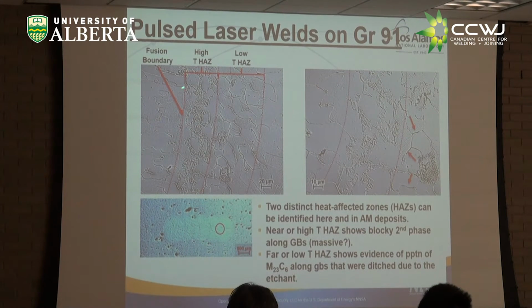So if you look at the back end of one of the pulse boundaries here, you see that what begins to happen here is this featureless, you can see things that are reminiscent of this featureless region, and then also things that are reminiscent of the speckled region that we saw before. It then sort of suggests that there is a low temperature and a high temperature heat affected zone. In steel terminology, the low temperature one would probably be referred to as an intercritical. The featureless region is a higher temperature heat affected zone. Not exactly sure what's coming out right there yet, but it allowed us to spatially separate and know the geometry of what was going on, and to realize that the speckled region and the featureless region, in that big yellow micrograph I showed you, are formed in the heat affected zone of a given pass when a subsequent pass is made.